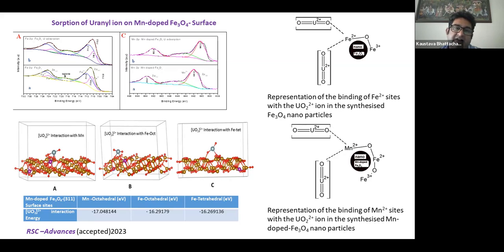So we have taken the solvation part to be constant. Post taking the solvation part to be constant, the ionic or electronic interaction of the uranyl ion with the Mn doped surface and the Fe3O4 surface, that is, we have taken an Fe3O4 311 surface, and we have calculated the energy. We find that whatever we find experimentally, what we see from our XPS can be directly evidenced from the theoretical model also.